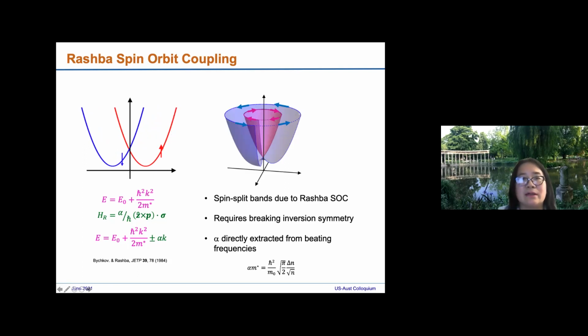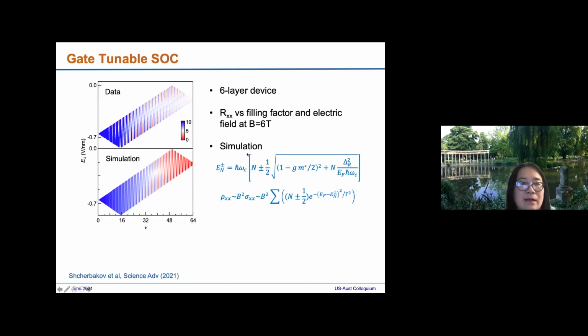So for example, in the outer band, the spins go around like this, and in the other band, the spins go around like that, the other way. And the nice thing is that we can extract the alpha directly from the beating frequency. We can just pick up where the nodes are, and then we can directly calculate alpha.